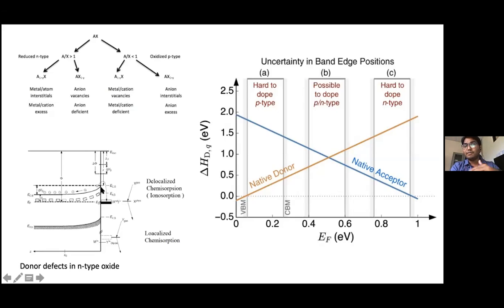Correspondingly, the potential here will show an upward rise. You will have some depletion layer created on the surface because of these surface states. Similarly, one can imagine that for a p-type semiconductor, you will have downward bending bands, which essentially denotes that you will have hole accumulation on the surface. It is the opposite of depletion in the case of holes. So all these defects which are interior give you some kind of donor or acceptor levels. Those on the surface are going to give you some kind of band bending or depletion layers, and that will result in changes in the electronic or optical transport.